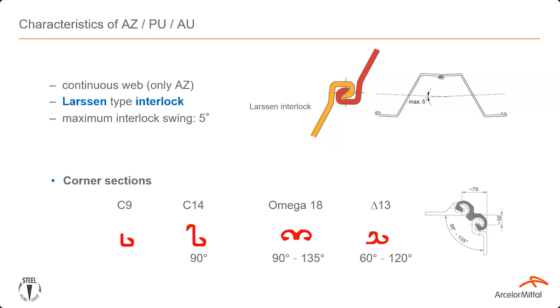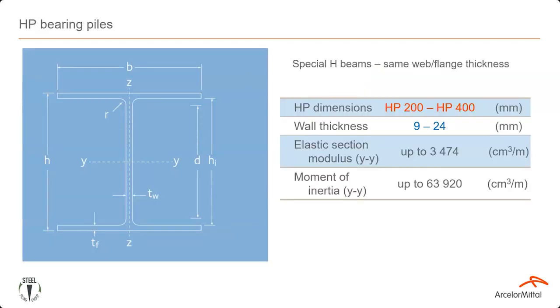If you look at the free corners, such as the C14, Omega 18, and Delta 13, these ones, they are mechanical interlocks, which means that you can connect them on a sheet pile interlock, and you can achieve a specific angle deviation as listed here. But if you need something more specific, then we can suggest the C9 section. It's more adaptable. You can weld it at any point on the sheet pile and at any angle, and achieve any tricky angle deviation, say 20 degrees, for instance.